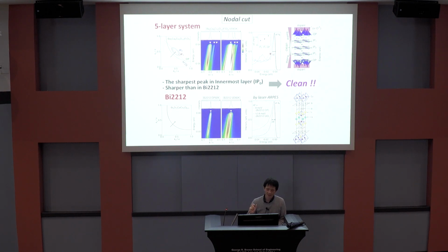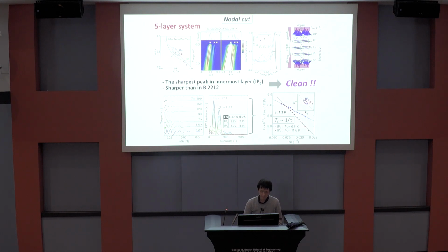That means the lifetime of a quasiparticle is getting longer, so our pocket really comes from the innermost layer. This trend is also confirmed by the quantum oscillation, which can also give the scattering rate. We found that the scattering rate is much less for the smaller pocket, so our pocket is really clean.